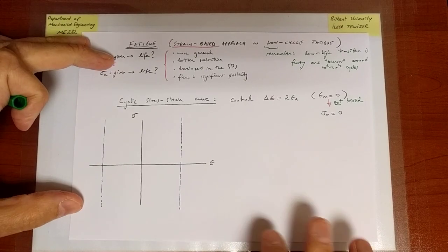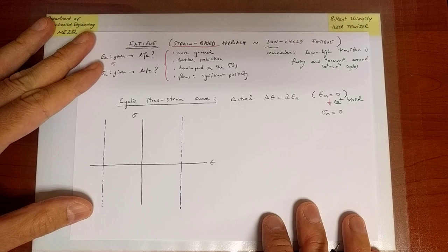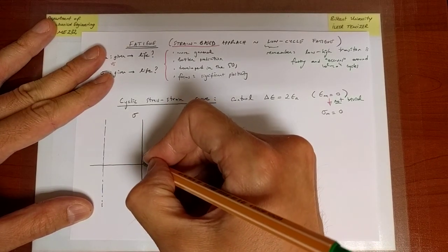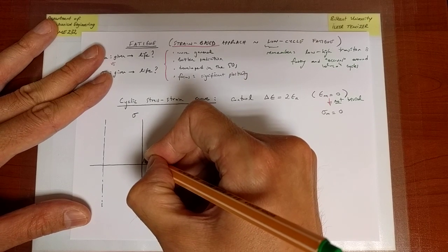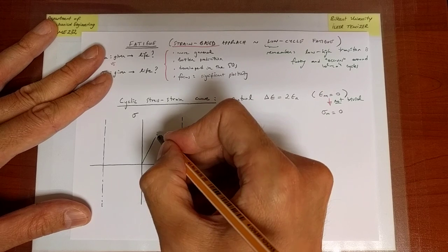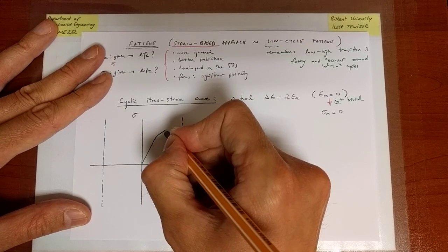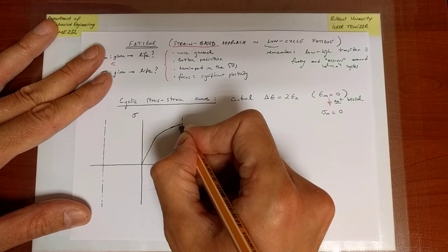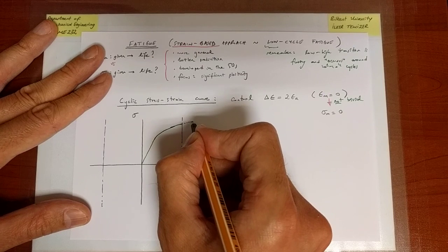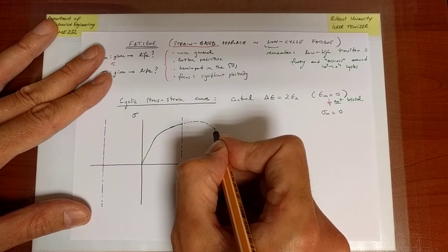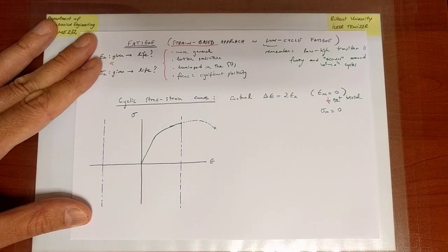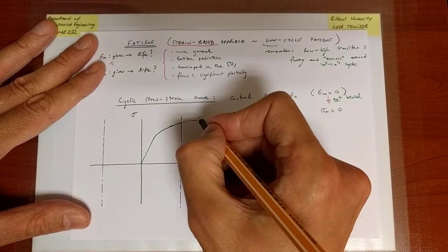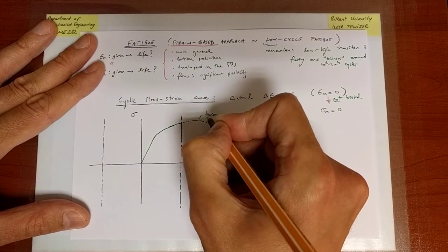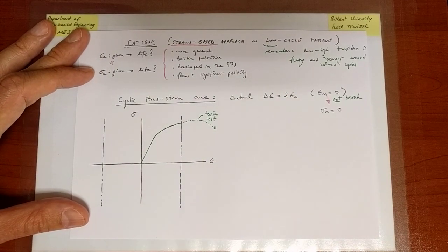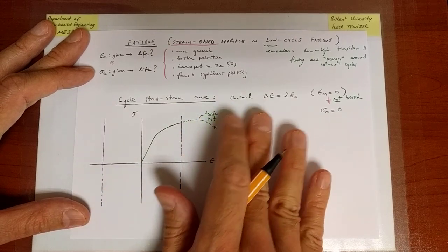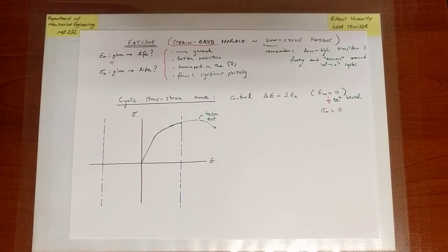Now, suppose I did a uniaxial standard tension test. What we would have in that scenario is an elastic region, and then a sharp or a smooth transition into a region where we clearly see plasticity, and then the stress strain curve would proceed, and eventually lead to failure. That would be the case of a tension test, a uniaxial loading scenario where we monotonically increase the strain, and then we try to see what happens.